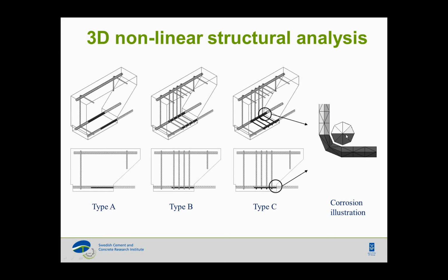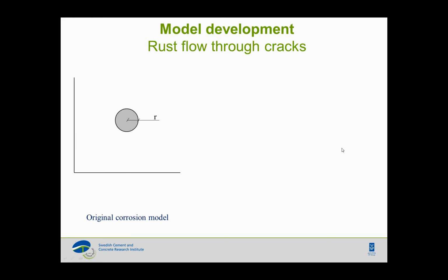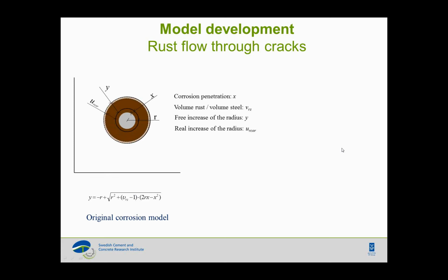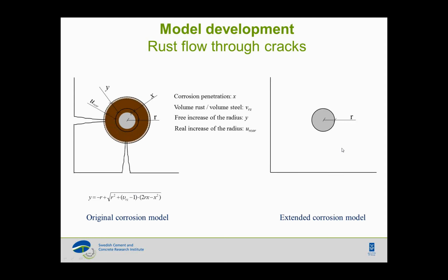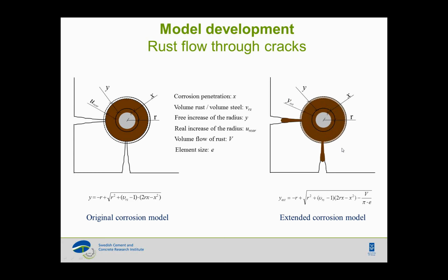Starting from the original model, if you think about a reinforcement located at the corner of a section, we start from a non-corroded bar with a radius of r, then we have the corrosion penetration, and what happens is that we have the expansion around the reinforcement, and since we have concrete around the reinforcement, that gives a little bit of pressure on this rust, but in the end we have the cracking. So we try to reformulate this, starting from the same condition with the corrosion penetration and the expansion of corrosion product, but this time, as soon as we have the cracking, we allow the rust to flow out. We calculate how it is flowing out by measuring the crack widths in the simulation. And then we still have the concrete around the reinforcement, meaning that we still have some pressure on the rust, so we have a little bit of compaction there as well.